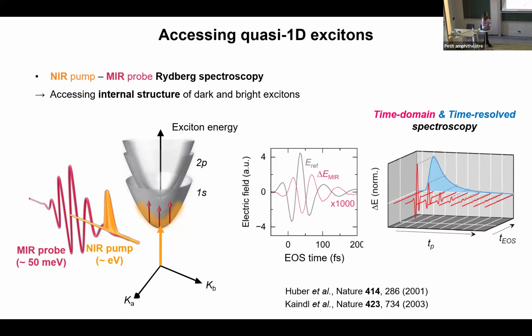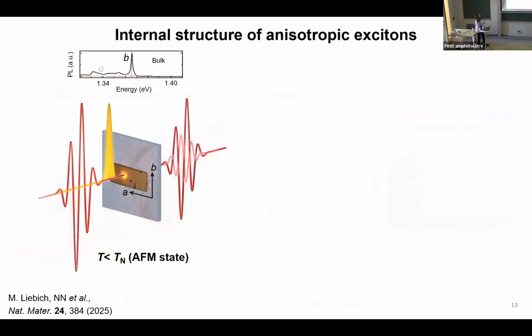So now with this time-domain and time-resolved mid-infrared spectroscopy approach, we want to study what we can learn about magnetic excitons in chromium sulfide bromide. We focused on the bulk, in its antiferromagnetic state. I just remind you that in chromium sulfide bromide, the PL emission is highly polarized along the B direction because the excitons are really emissive only along this direction, while they have a really small transition dipole moment along the A direction.